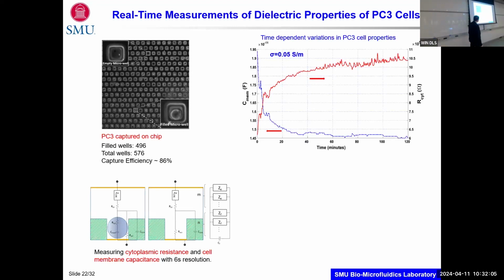So we did this at a conductivity of 0.05 Siemens per meter. The top red figure shows the cytoplasm resistance, and the left, which is blue, is the membrane capacitance. As you can see, there are some changes in the membrane capacitance, not as significant perhaps, but there is more change with the cytoplasm resistance. It's because the ion channels on these cells, which are PC3 prostate cancer cell line, are constantly interacting with that media, and then it shows this variation.